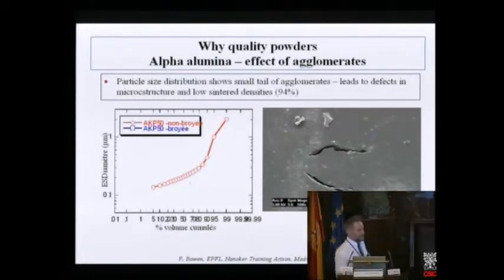If we look at the microstructure after a simple slip casting and sintering without optimization, we see this big defect. So this powder is a commercial powder, high purity, but to transport dry powder, all manufacturers spray dry. Even if the powder is not meant for pressing, they spray dry to facilitate movement. Particles less than a micron are too difficult. They don't flow. You can't fill bags. So this is a hard granule from the spray drying, which becomes a defect in the ceramic and will kill your mechanical properties.